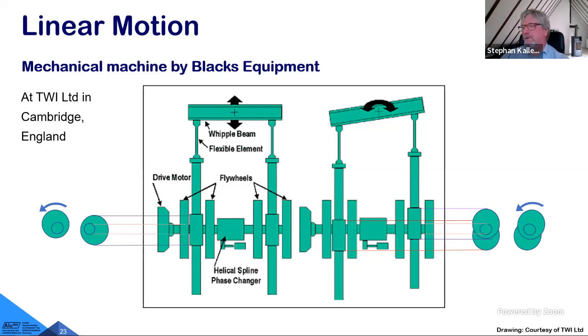This is a complicated gearbox, and on the left-hand side we see the linear motion being generated, so plus and minus, let's say, 3 millimeters of amplitude. And on the right-hand side, we see that the beam only swivels around that pivot point. So this pivot point does not move up and down anymore. To achieve that this goes really to 0 at the end of the weld cycle, we just use 2 eccentrics on the same shaft, which is driven by an electrical motor from the side. If you align them in a way that they are misaligned, then the beam swivels. And if they are in phase and then rotated, as shown here in the left-hand picture, then this whippletree beam moves up and down or forward and backward.